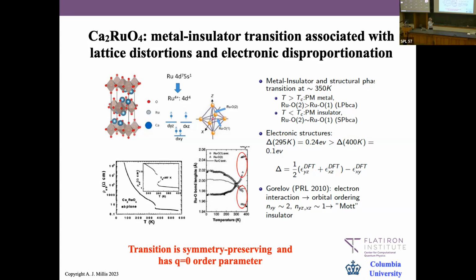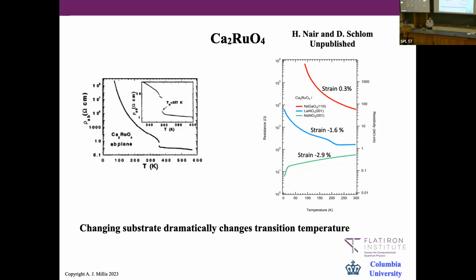You go in the high temperature phase from a case where the three relevant ruthenium orbitals are equally occupied to, in the low temperature phase, one orbital doubly occupied and two singly occupied. So there's a mixed electronic and lattice transition.